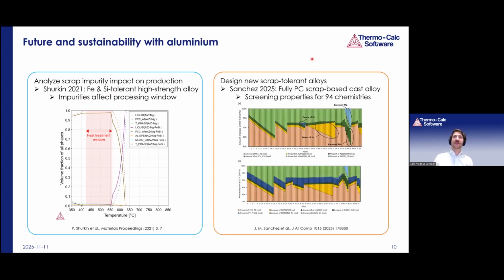And another more recent paper, which is quite nice, by Jon Michael Sanchez et al. from this year. They designed a fully post-consumer scrap-based cast alloy. They had sorted scrap in maybe 6 different categories, different chemistry ranges, basically. And they did a high throughput calculation in Thermo-Calc to screen the properties of 94 different chemistries. And they made these quite interesting diagrams. These are column diagrams showing the volume fractions of all the different phases at different temperatures.